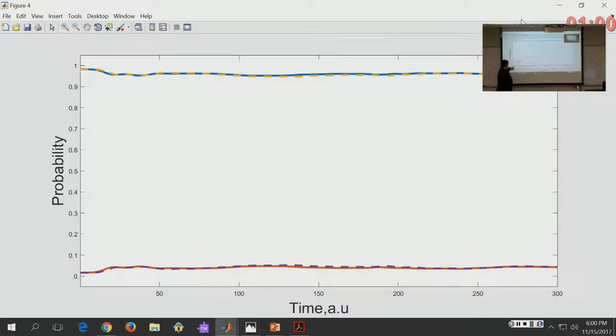So you see that the transfer is going on, but it is much slower. So this distance of 2 atomic layers missing between slabs, it is almost insulating. It forbids the transfer. So probably it is not the best structure for photovoltaic generation. So one may need to establish some bridging structure, bringing them closer.